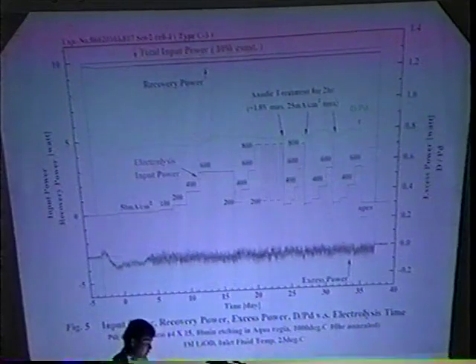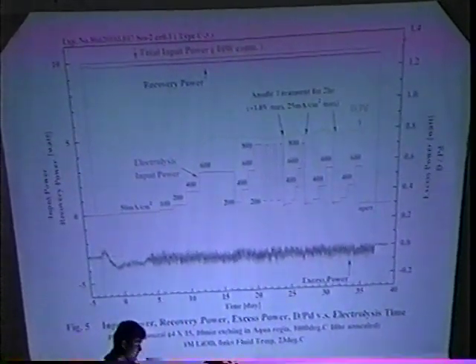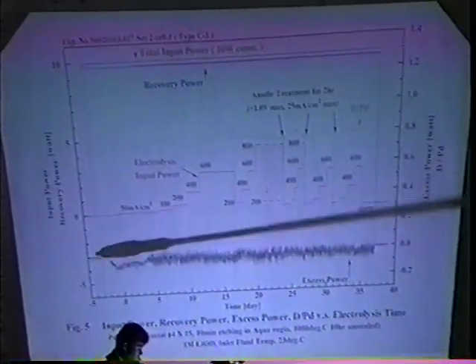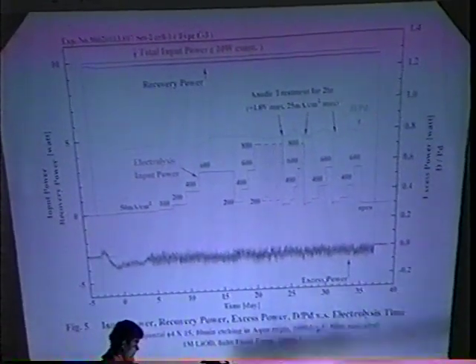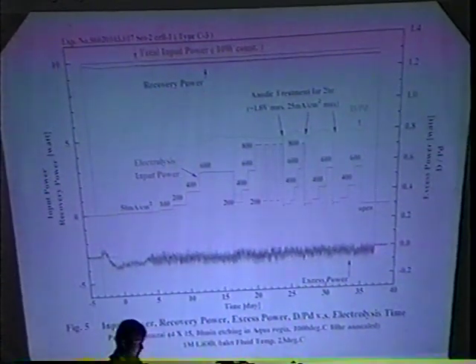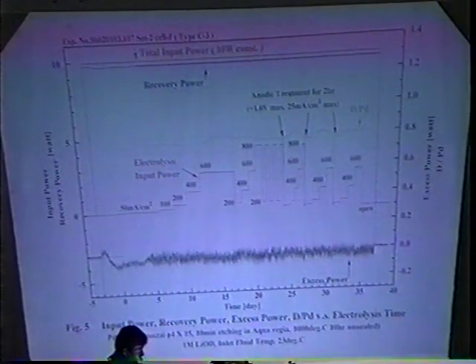And this figure shows the detail of the calculated result of excess heat in the same experiment. Excess power is plotted on the right axis in this figure. This part is the first measurement. It is presumed that the recovery of heat was unsteady because of the complexity of the heat exchanging tube. Excess heat was almost plus minus 0.1 watt during the whole experiment. So it was decided that excess heat was not observed in this experiment.